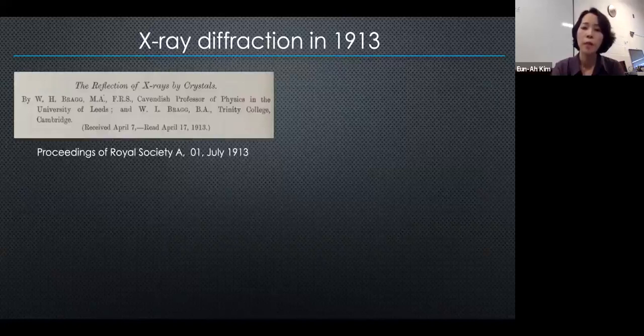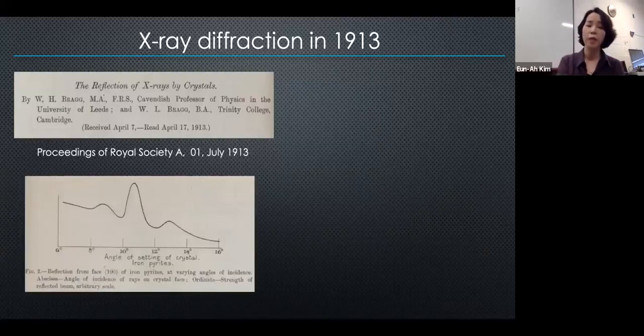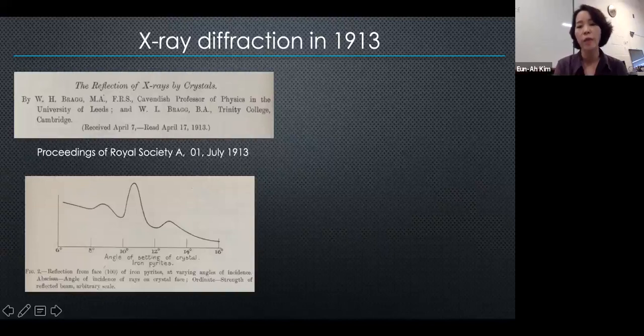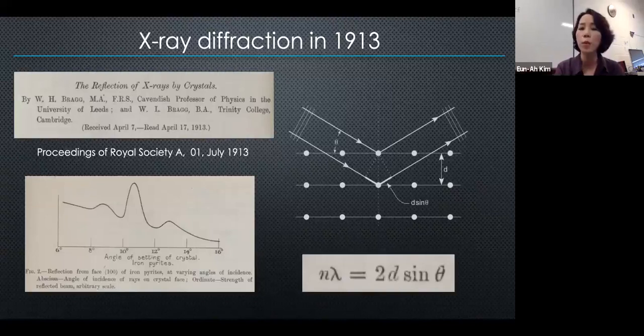X-ray diffraction in 1913. This is a snapshot from the original paper that was a Nobel Prize winner by father Bragg and son Bragg. What was described in this paper is perhaps the first successful example of what we now call forward modeling. The kind of data they were looking at in this paper was again this kind of curve. They are changing the incident angle of the X-ray beam, and they're measuring the intensity. And as they change the tilt angle, there's only one angle that they're changing, and they're obtaining these kinds of curves. These curves were successfully explained by this forward model that Bragg and Bragg put forth, which gives rise to the Bragg condition that we now learn in introductory physics.